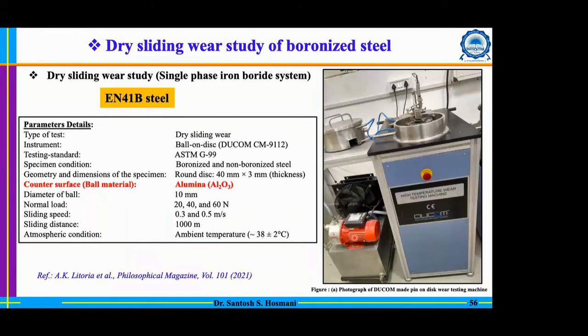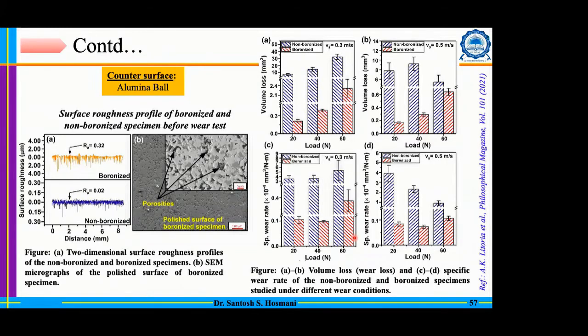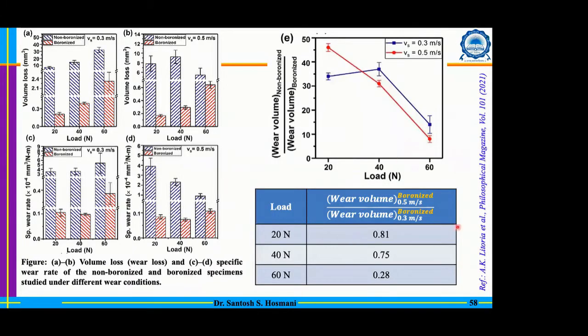Okay, so due to lack of time, I'll just quickly run through this and give you the information which is crucial here. I mentioned that we did the boronizing wear loss study at different sliding speeds. You can see in that table that the wear volume at 0.5 meter per second sliding speed with respect to 0.3 meter per second sliding speed has a ratio less than 1. That means at a higher speed, your material is performing very well. And the gap between their wear behavior keeps on increasing as you keep on increasing the load.